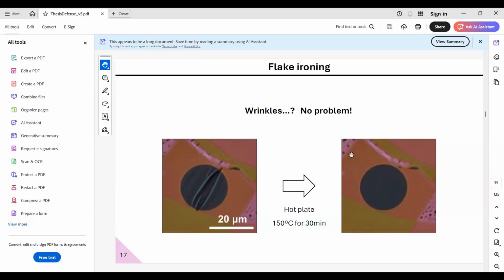To be honest, I don't know if it oxidizes, but if it does, it probably oxidizes from the very first instant that we prepare it, because we don't see any change in their properties with time. We have this kind of materials suspended for many years. Even monolayers of these materials remain suspended for years. I would say if there is a bit of a degrade of the crystal structure, these materials would collapse. They are very fragile, very thin, and so they break.